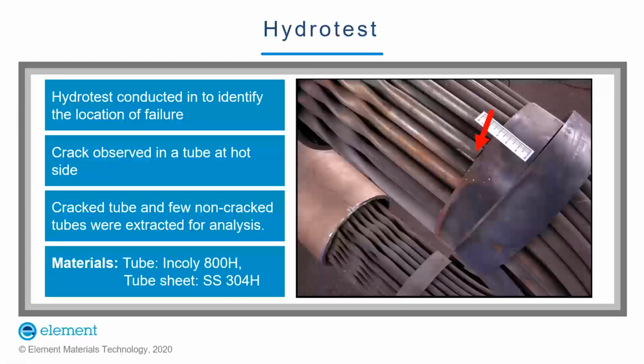After the hydro test, the shell of the heat exchanger was cut open and it was observed that one of the tubes cracked at the hot side of the heat exchanger. It was also noted that the crack was very near to the stabilizing strap as shown in the picture. This cracked tube, which from now on in this presentation will be called the failed tube, was extracted along with a few other non-failed tubes. These tubes were examined for establishing the root cause of this failure. As mentioned before, the material of the tube was Incoloy 800H, which is an alloy used for high temperature application.